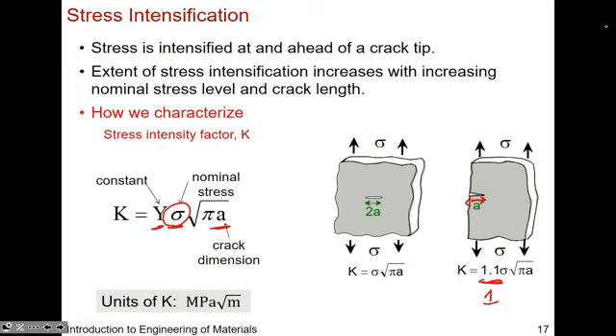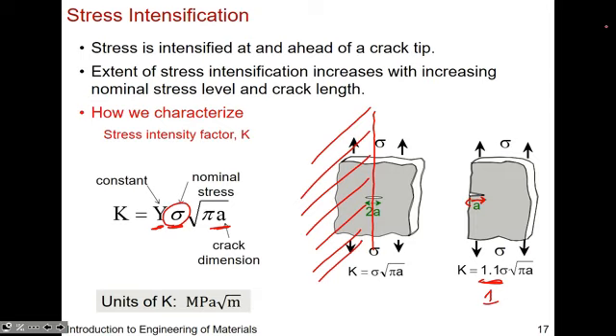Your internal crack, we treat that as 2 cracks. So if you consider, right, if you just block off this part, this looks like this, right? So we treat an internal crack like it's just 2 surface cracks. So your crack that's on the inside is 2 crack length, because we're treating it as 2 cracks. Whereas your surface crack is just that. That's how we define crack length. So internal is 2A, or if you're given the internal crack length, then A is just divided by 2.